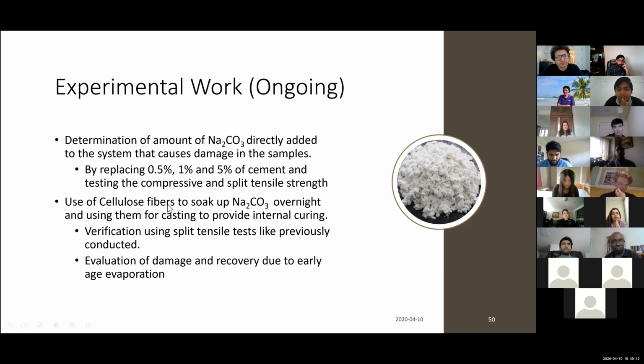One more method that we would like to use to introduce sodium carbonate inside the system without causing damage is to use cellulose fibers to soak up the sodium carbonate solution. We leave the cellulose fibers soaked in sodium carbonate solution overnight, and then use them the next day for casting, and then we can test for verification using the split tensile test or the evaporation test that we did earlier. This ends my presentation, and I'll be happy to answer any questions. Thank you.